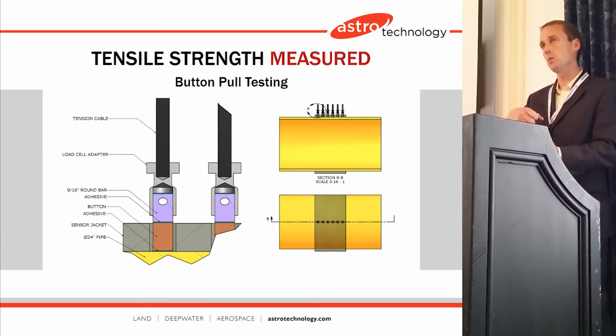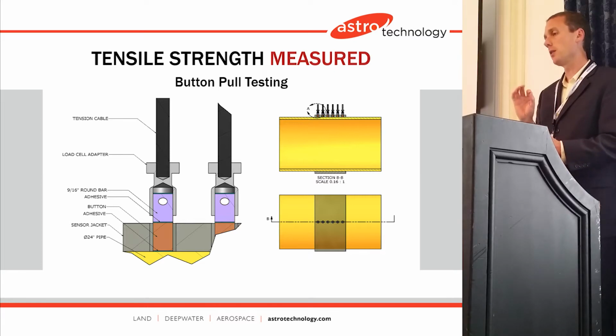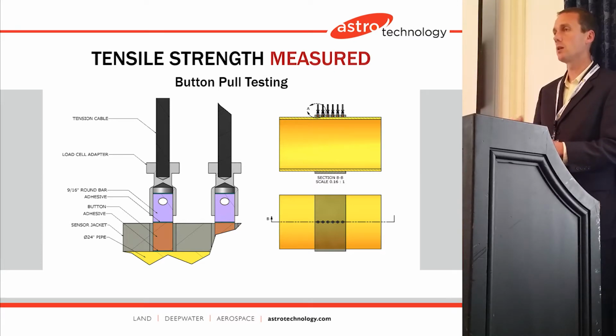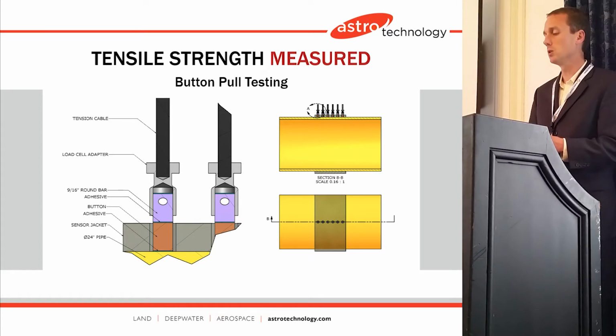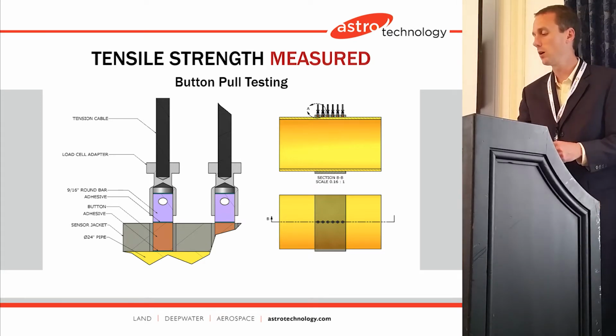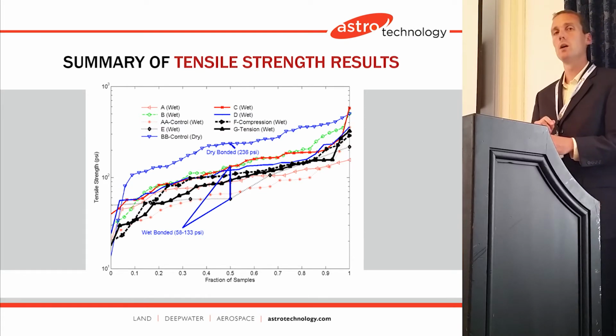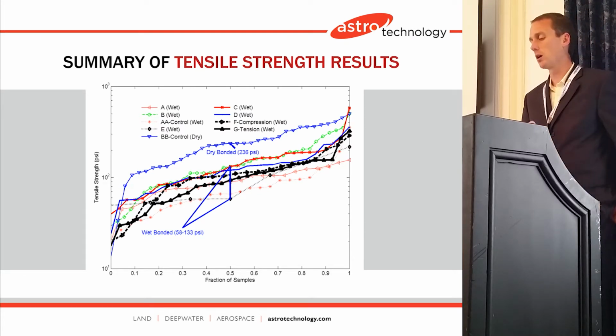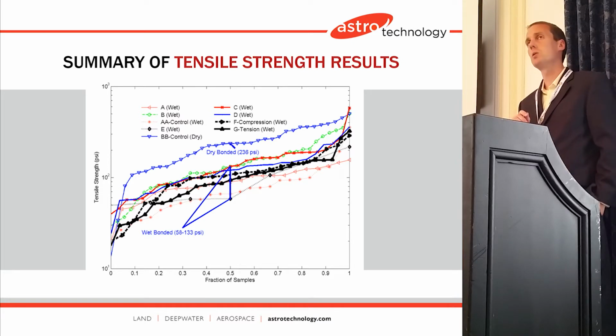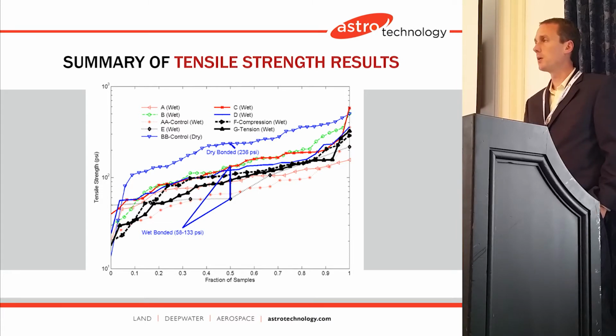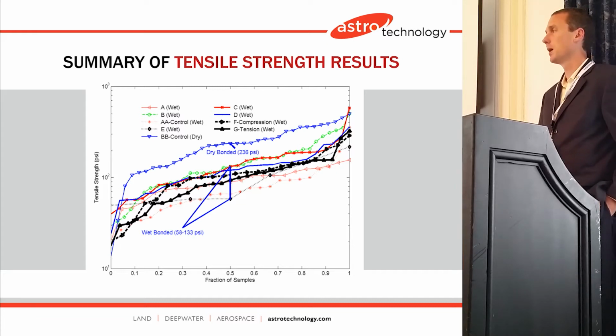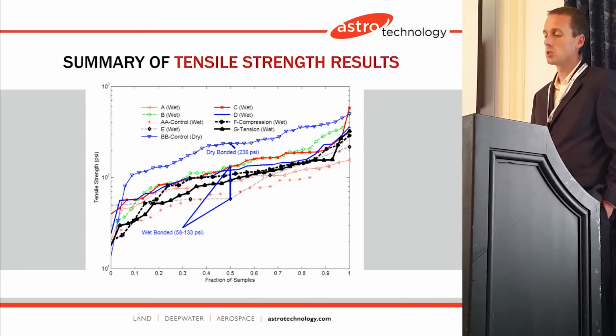And this is a mechanism that would take that button and then pull up. And so we monitored the force as it would pull up. At the point that the force decreased, that was the point at which we recorded the yield strength. And we did this for a number of samples. Each point on this plot, this is a semi-log on the Y scale, shows the yield strength for each of these buttons. And so we had a number of different test clamps that were applied both for the four-point bending test, but also for the compression and the tension.